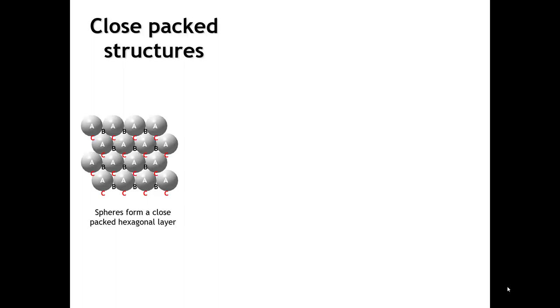Okay, so now let's take a closer view of metallic solids. If I were talking about a two-dimensional array of spheres, and I said, let's arrange these spheres in the densest possible arrangement, you would come up with this kind of a layer, which basically is a hexagonal close-packed layer. I would have a hexagonal unit cell that would probably look something like this, with an atom on the corner of each lattice point. You can see that each atom has six neighbors that are touching it. This is the densest way to pack spheres in two dimensions.